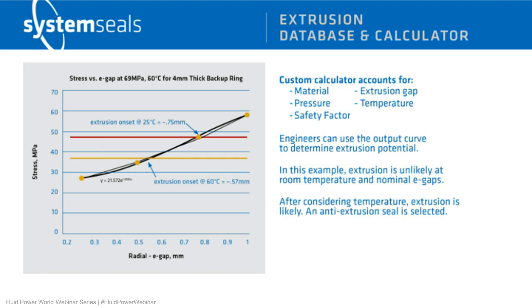And in this case, at 60 degrees Celsius, this calculator tells us that extrusion will actually onset closer to 0.6 millimeters. And so in this case, we have a couple of options. We either have to redesign the sealing package, select a different material, or perhaps install an anti-extrusion backup ring. But again, we couldn't really perform this step until we understood what the true extrusion gap was that we obtained out of that bearing calculation that we did initially.